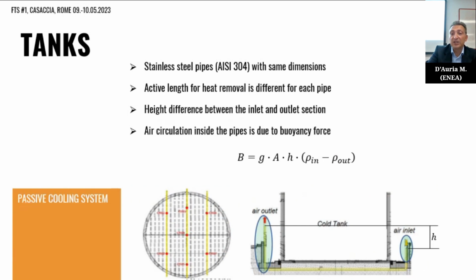So for a passive cooling system, all pipes have the same dimensions, that is the same diameter and length. But for each pipe, we have a different active length for heat removal. Active length decreases if we move from the center towards the perimeter. It is possible to use stainless steel AISI 304 because it is not in contact with molten salt, but only with air. So there is a height difference between inlet and outlet section to ensure a chimney effect and to enhance the heat removal. So also buoyancy to ensure air circulation inside the pipes.